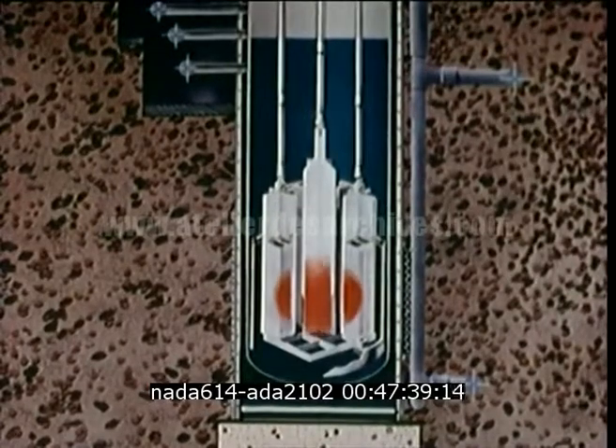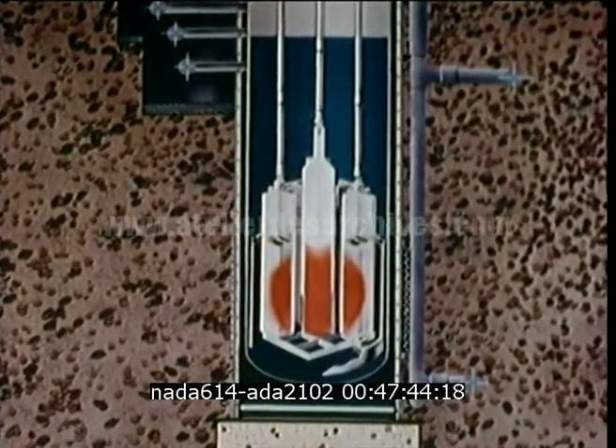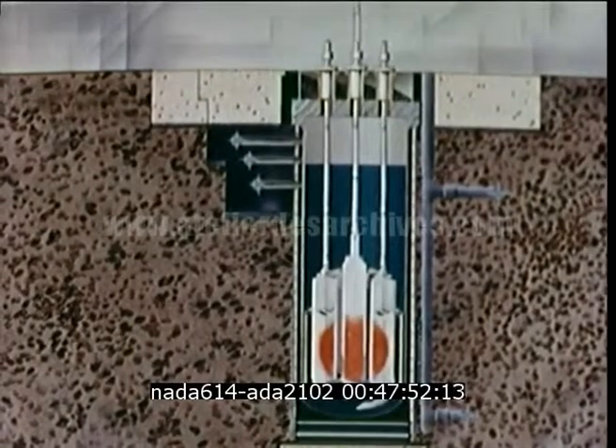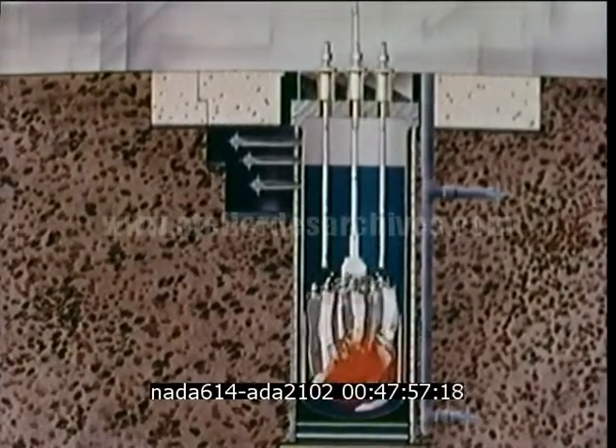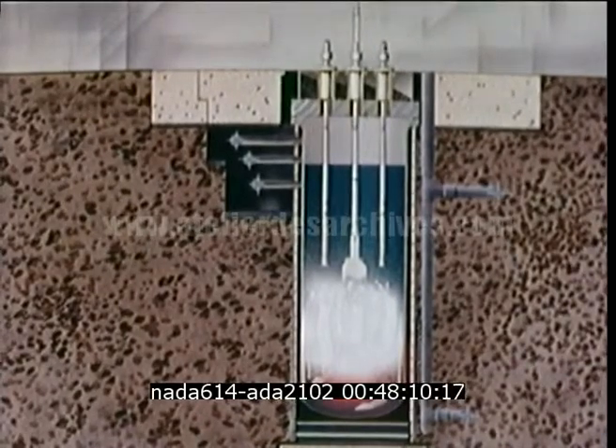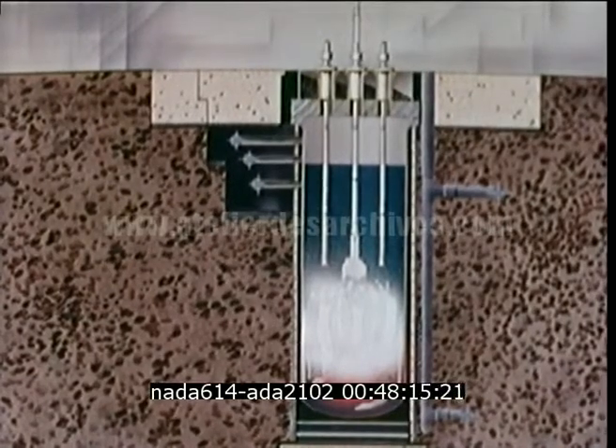The fissions occurring within the fuel plates increased the temperature of these plates to a point near or above melting, depending upon location in the core. In the center regions of maximum neutron flux, the fuel within the plates experienced vaporization temperatures and burst the plate cladding. Thus, the spewing of hot vaporized fuel rapidly produced steam in the surrounding water. The steam was generated at a rate far faster than could be dissipated, and the resulting outward expansion of this high-pressure steam bubble of at least 500 psi damaged the core.